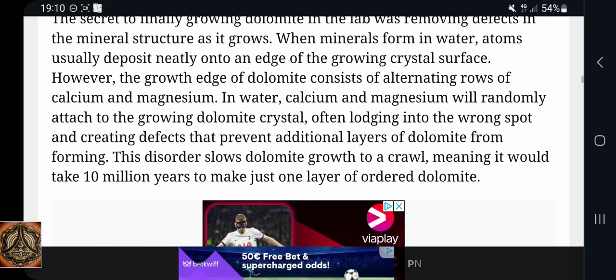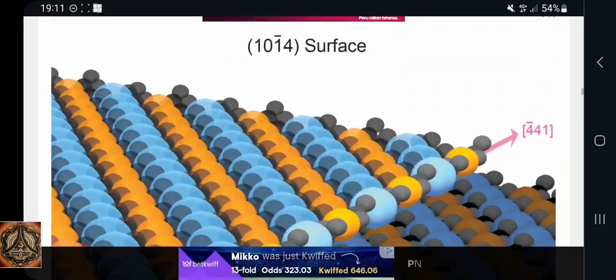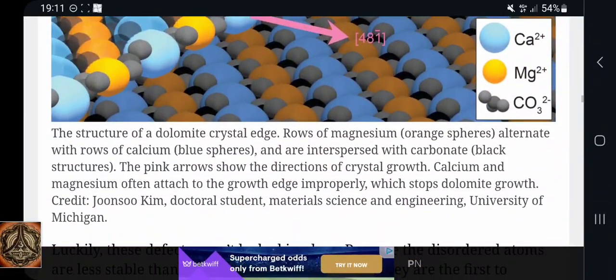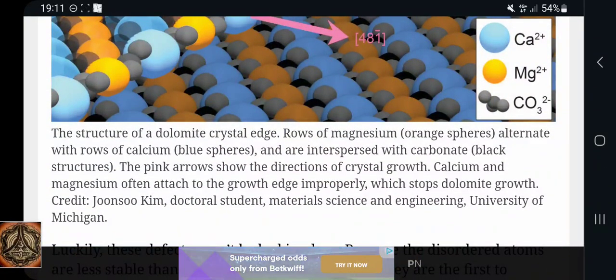In water, calcium and magnesium will randomly attach to the growing dolomite crystal, often lodging into the wrong spot and creating defects that prevent additional layers of dolomite from forming. This disorder slows dolomite growth to a crawl, meaning it would take 10 million years to make just 1 layer of ordered dolomite.